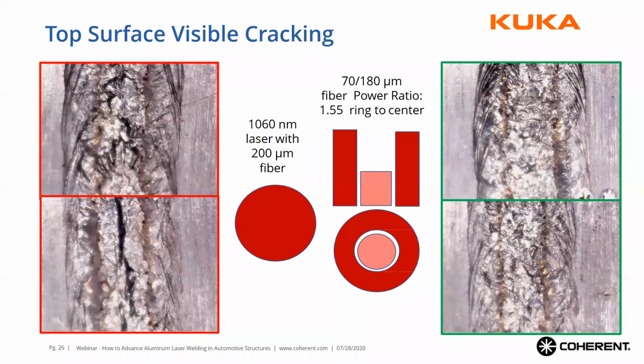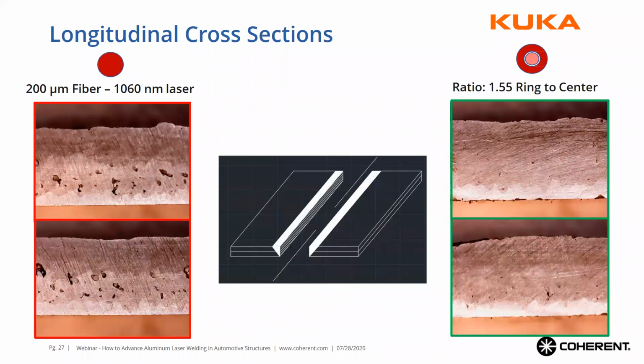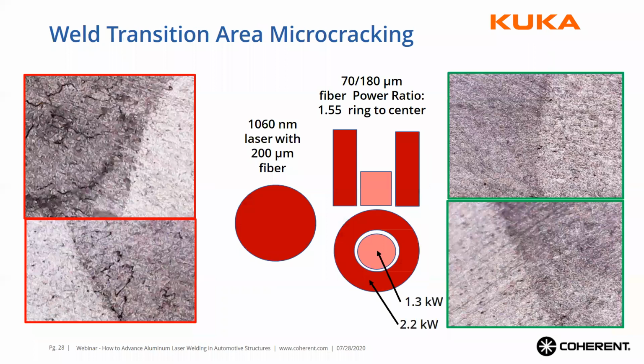Beautiful weld. Now looking at the longitudinal cross-section of these two welds, you see on the left side the standard fiber laser shows a lot of porosities, especially near the bottom of the weld and the root where you'd expect to see it. And on the right side, very little porosity for the ring fiber laser weld. Looking at the microstructure of these welds in the transition zone going from the weld into the parent material, you can see on the left side again the regular fiber laser showing a lot of micro cracks, whereas you can see the smooth transition on the right side with the ring fiber laser, and no micro cracking is visible.